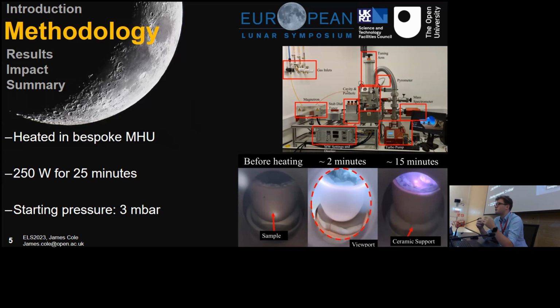That's the first result, is that we'd extracted water from these samples at a lower power than ever been done before. But then I reduced it to 25 minutes, as I wanted it to be at a point where we could compare the extraction throughout all the different sample types and different water contents. And yes, we did these experiments at 3 millibar, and through the use of spectral identification and some mass spectrometry, we were able to identify that, yes, it was the water vapor that was being produced. So the figure on the bottom right with the purple plasma is actually the water vapor being produced. I should say that extraction in this case is measured simply by comparing the mass before and after heating.